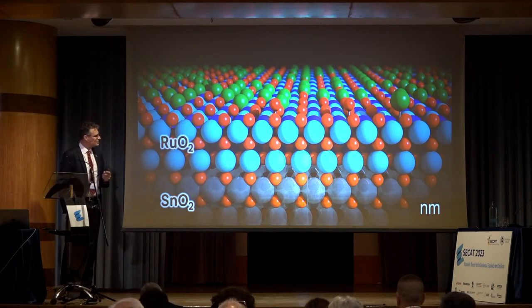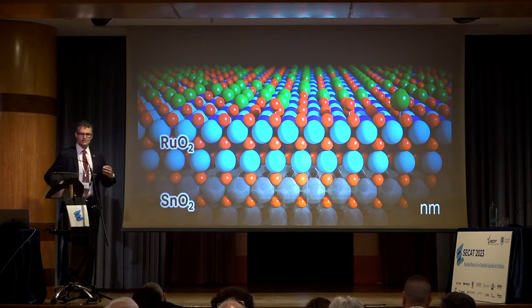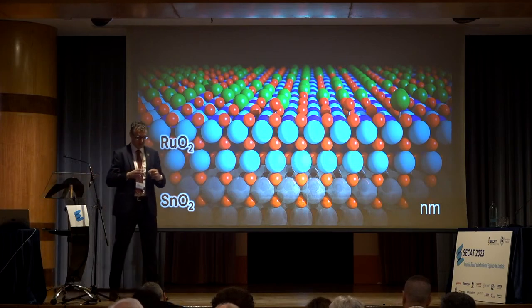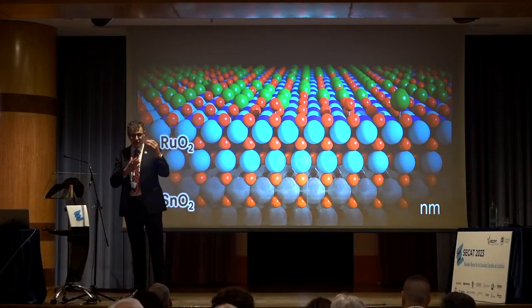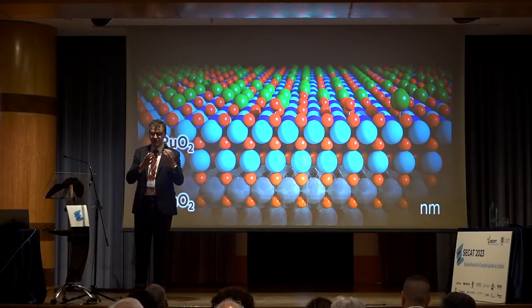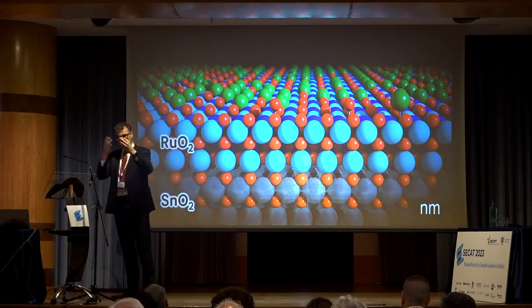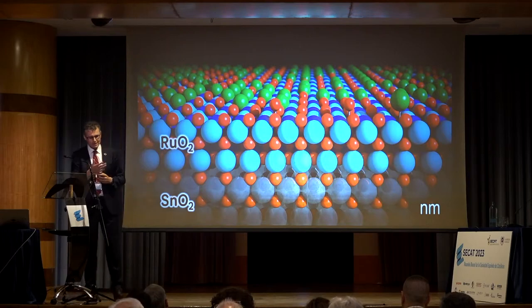What happens there is that hydrochloric acid splits, as you have seen in the picture. Oxygen dissociatively adsorbs. Oxygen and hydrogen, so the HCl bond is broken. You form hydroxyl groups. 2 hydroxyl groups recombine to produce water, and 2 chlorine atoms recombine to produce molecular chlorine.